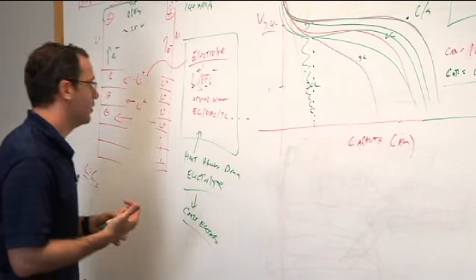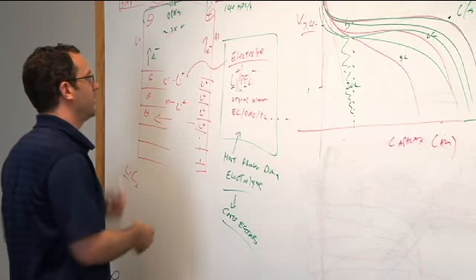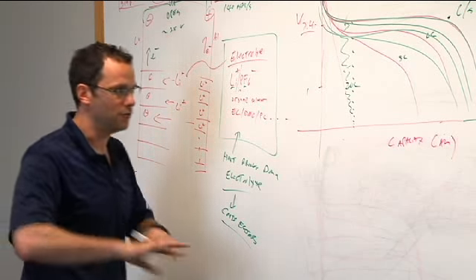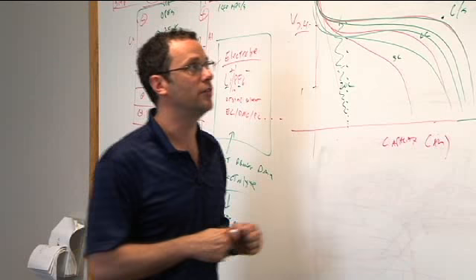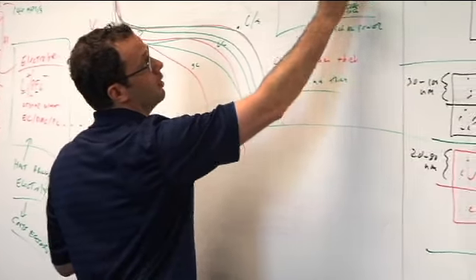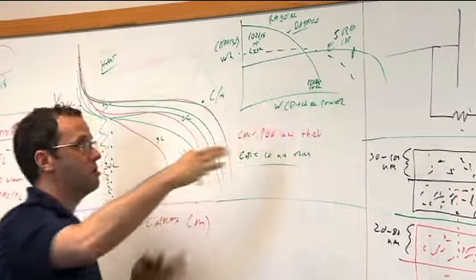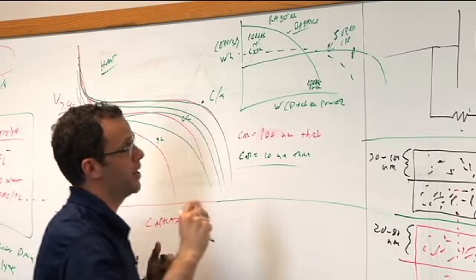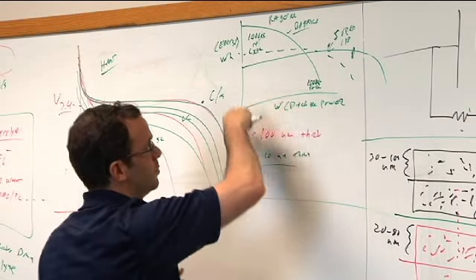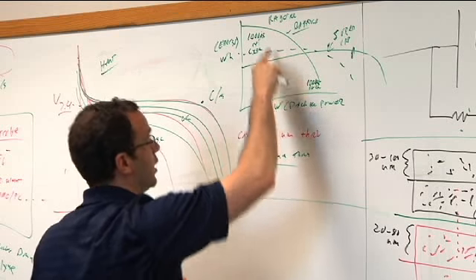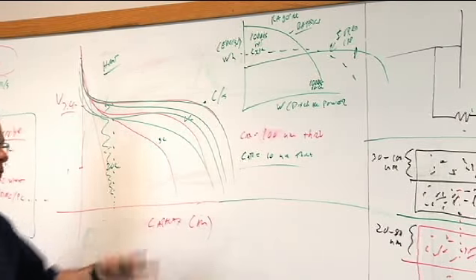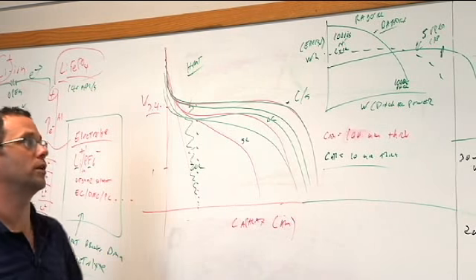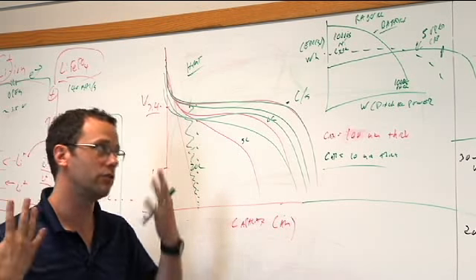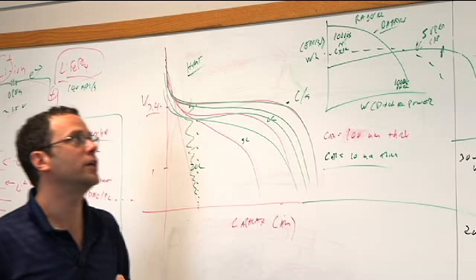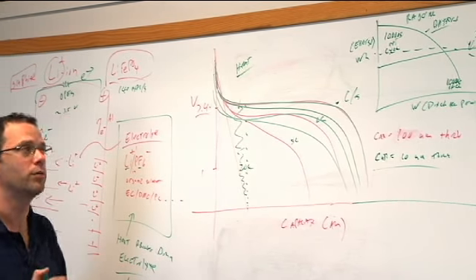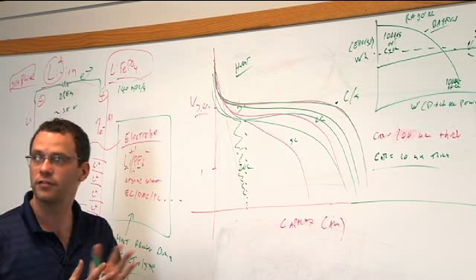And they basically have super high rate, very thin intercalation electrodes that have really almost no capacity fade. And their Ragone plot is somewhere in the middle, like this. They're also really expensive though, but you might end up using those instead of a supercap. You get more energy at these higher rates, and you could still maximize the efficiency of your system without having too much degradation according to the heating and all this that's happening. So that's another interesting option. I hope to get some samples at some point, and it'd be really fun to play with those too, especially since you guys are starting to tool up and have some legitimate stuff, which is cool.